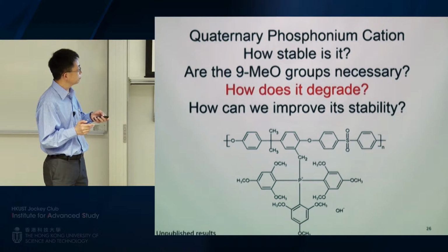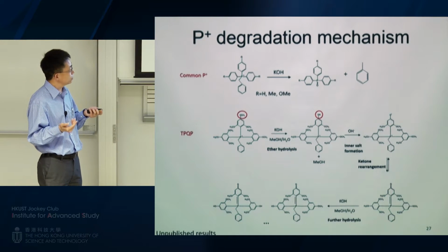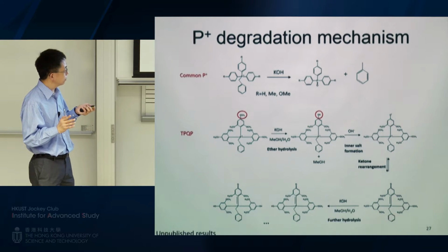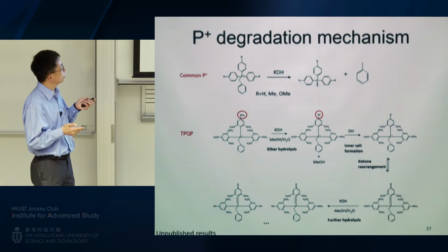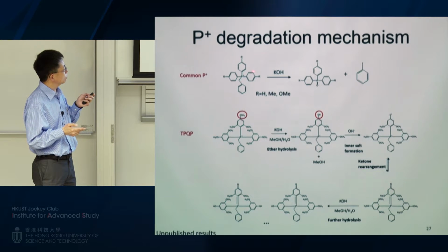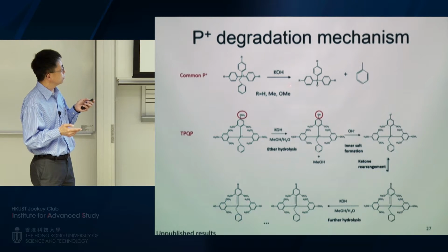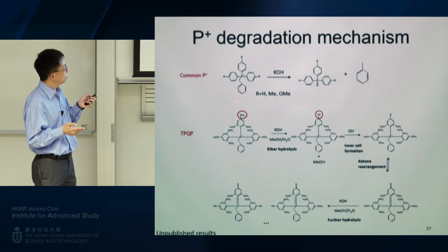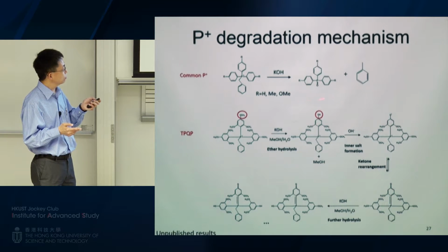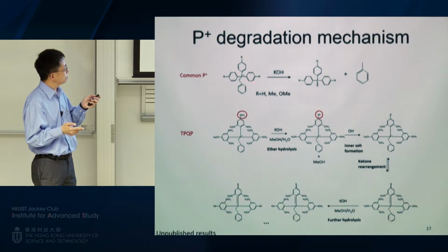So how does it degrade? It took my student Bingzi Zhang a long, long time to figure this out, so now I'm just giving you the conclusion. If you have the single substitution, the degradation mechanism is oxidation. Basically, you strip this side group away, and you put a double bond on the phosphorus, and you attach oxygen. So this becomes phosphorus oxide. This is how the cation goes bad, becomes neutral, and falls apart.